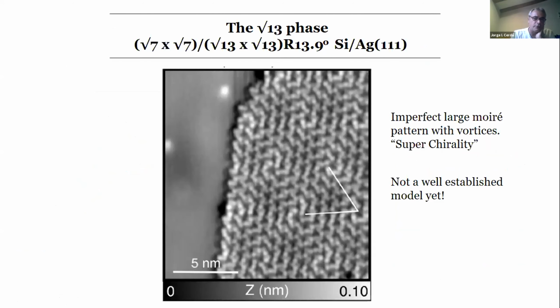Now we go to the most debated structure. It's probably the least studied, the most complex one, which is this square root 7 for silicon, and square root 13 for silver. Okay, this is a large image. We have a kind of super periodicity, more or less. It's not perfect at all, and also what I call a super chirality. You can see that there are some vortices. They seem to have some kind of chiral nature, although we have not really studied it in detail.